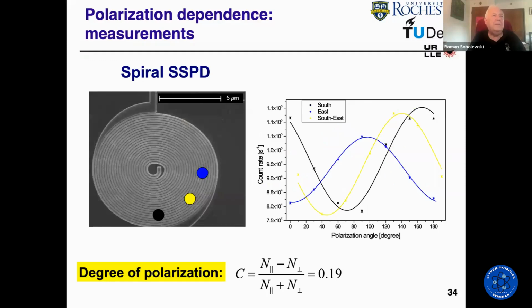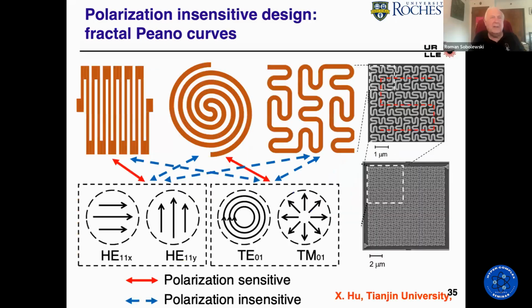Our friends at Delft also fabricated this kind of funny detector, where you can see the detector stripes are wound up in a kind of spiral, and they could look at different places and, of course, get horizontal polarization, vertical polarization, and 45 degrees. And again, if flooded, then there was no signal.